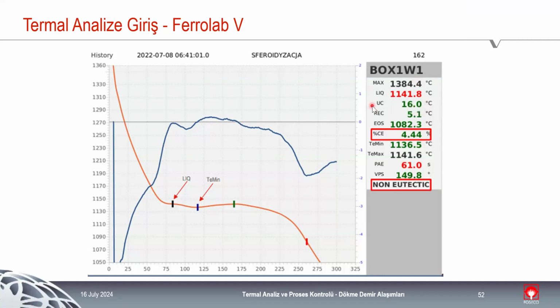The recalescence is the other value that we can study after magnesium treatment, and it is an important value based on the latent heat that is released during the nodularization of the cast. So it is basically what's happening between the theoretical minimum and the theoretical maximum. The temperature increases a little bit, and it increases because we have a phase being formed during that time, and the phase is graphite. So normally, if you have between 2 and 5 degrees recalescence for nodular cast iron, it's a good indication that the nodularization process was okay, and we don't have any problem.